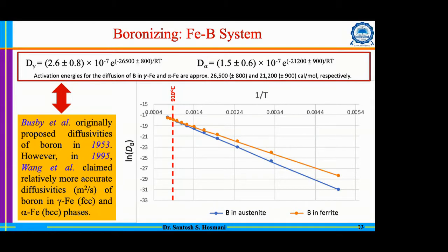Because in the case of carburizing, we need to be in the austenitic phase region because of the very high solubility of carbon in austenite. But here, that is not the criterion. We have seen in the phase diagram that solubility is not really great in both the phases. So that is not the criterion. The only advantage you get at high temperatures is that diffusion will be faster anyhow, and your process will finish early. That is the only advantage we can get.